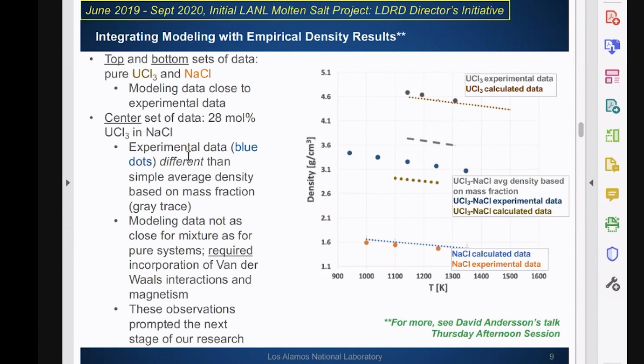But the bottom line here is that it's different than just simple correlations will tell you, than just simple average density based on mass fraction. So what this is telling us is that modeling data is not as close for the mixture as it is for the pure systems, and it required the incorporation of van der Waals interactions and magnetism, for example. And this is actually prompting the next stage of our research.